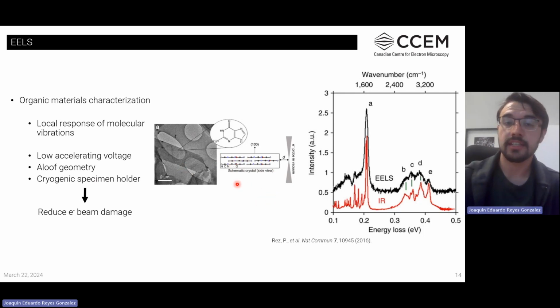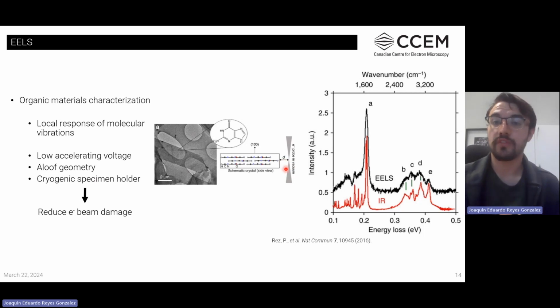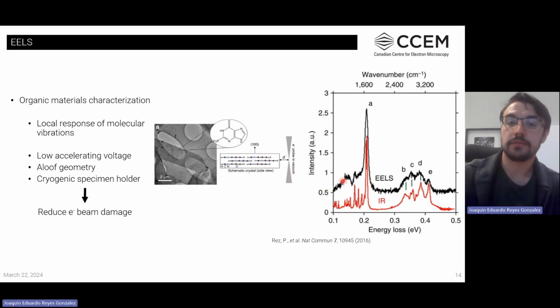This is actually an example of how an aloof experiment will be done. So you will have the crystal, and then you will have the electron beam at a certain distance in the proximity of the crystal, which will still show or reveal in the EELS spectra the infrared active modes, and yields this result that you see on the black line to the right.